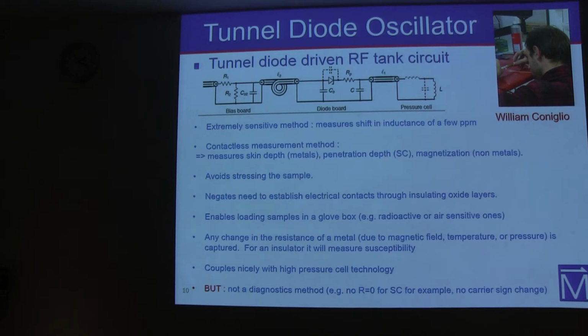For example, when you look at a superconductor and make a transport measurement, you know you got into a superconducting region when you go to a zero resistance state. In our case, for tunnel diode oscillation, we just see a shift in frequency. So if we want to make this kind of measurement, we need to have some prior knowledge of the sample, to know where to expect a transition, for example, and then follow the trend in pressure.